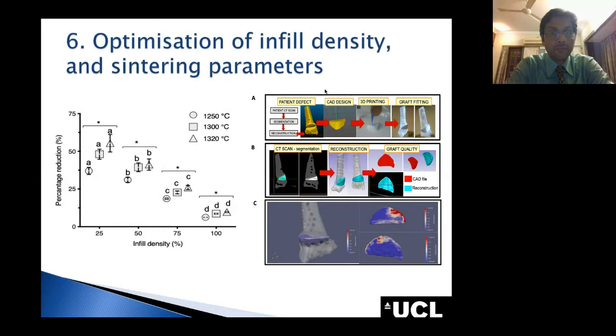And finally, as we sinter the scaffold, depending on the infill density, we will have a shrinkage of the scaffold itself. So we tried to calculate how much of this reduction was happening in each scaffold for each infill density, and we see that there is a linear relationship between the infill density and the percentage reduction. That allowed us to have some linear equations to decide on different infill densities and take into account the percentage reduction.